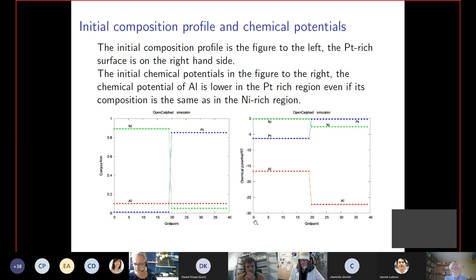These are the chemical potentials. The chemical potentials are what is driving the diffusion. So you see nickel here has a higher chemical potential than in the surface. So nickel will try to move to the surface. Aluminium also has a very high one; platinum decreases the aluminium chemical potential very much. So you have a strong jump in the chemical potential of aluminium. So this is the initial profile.